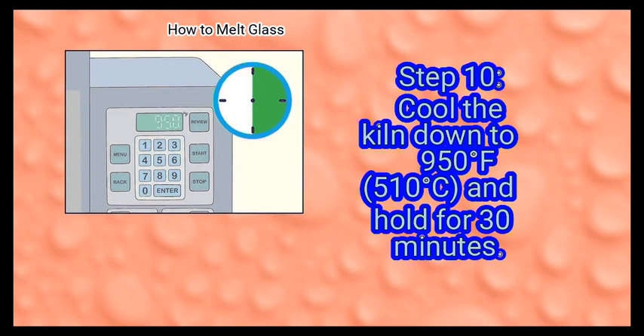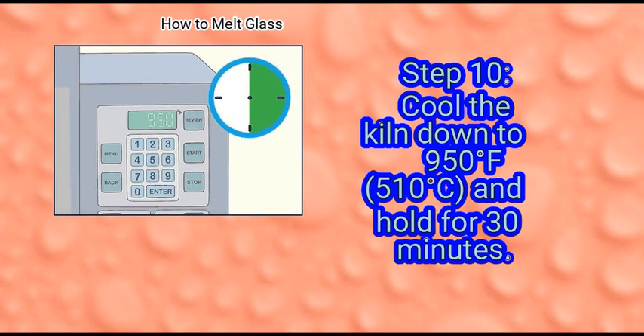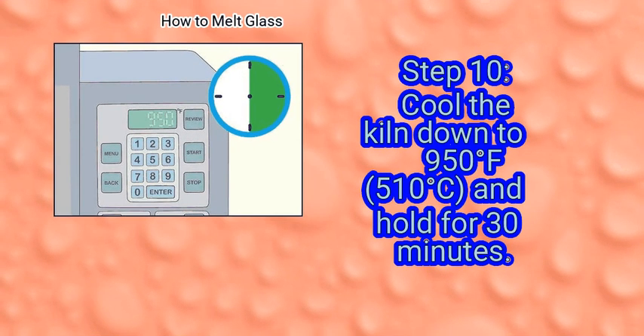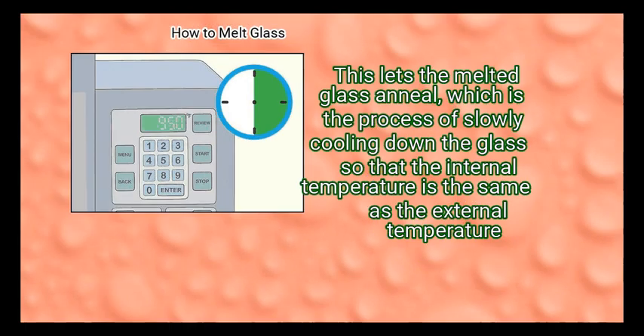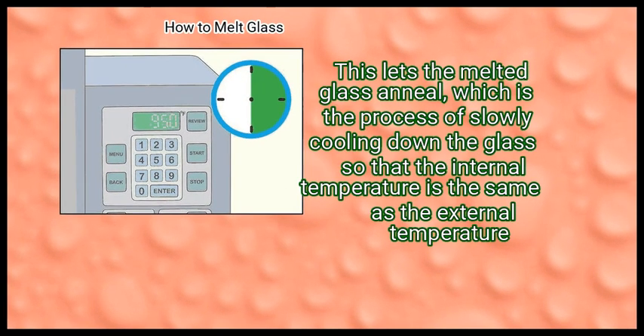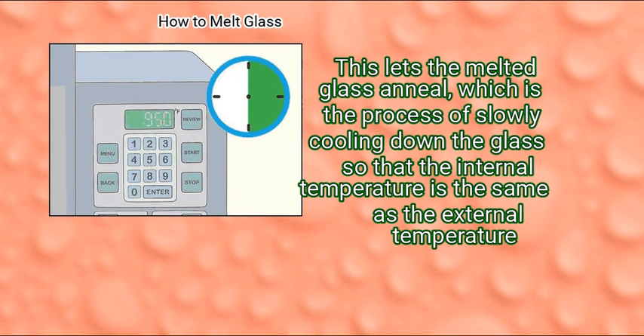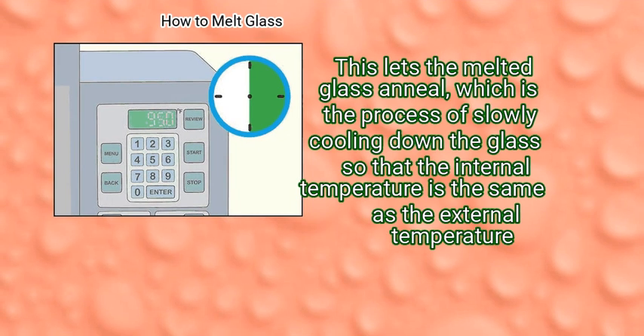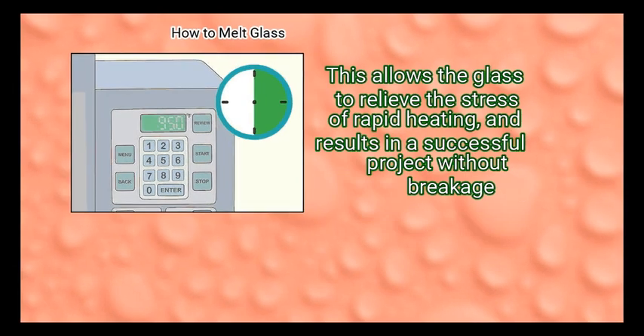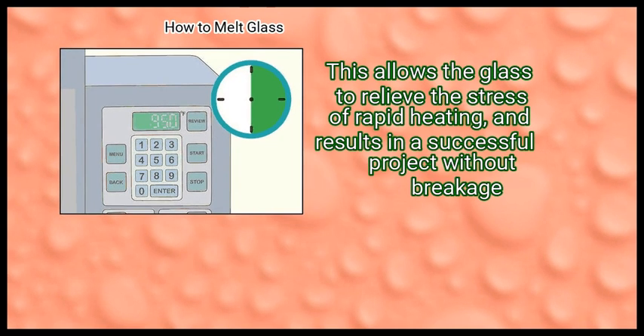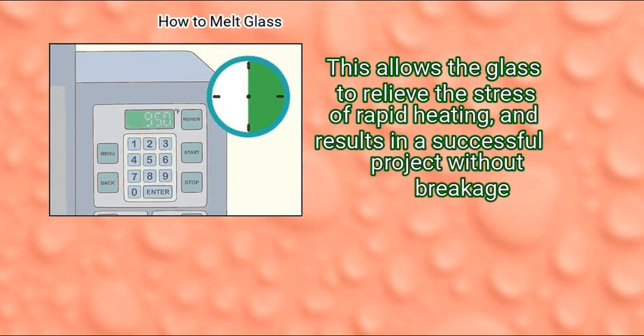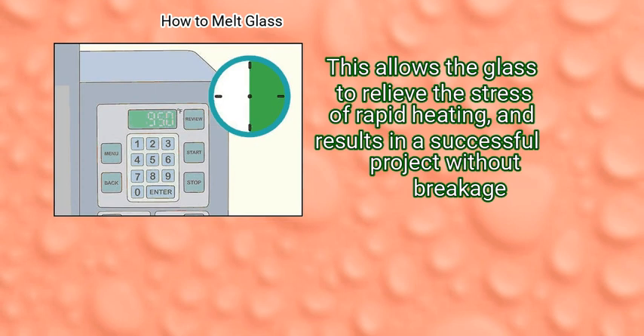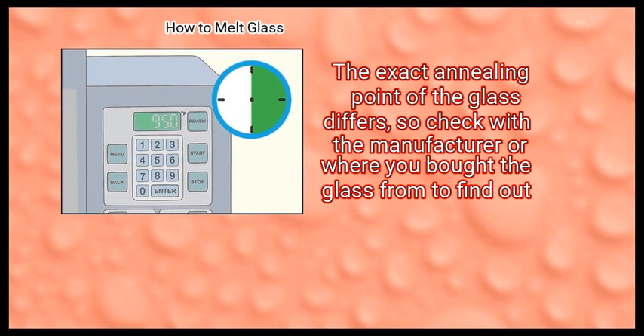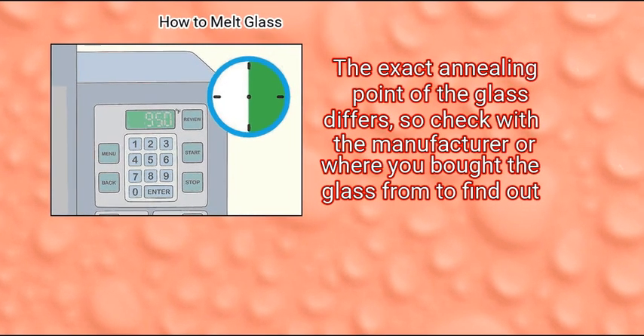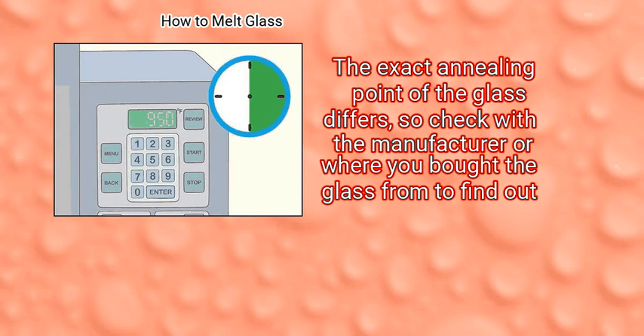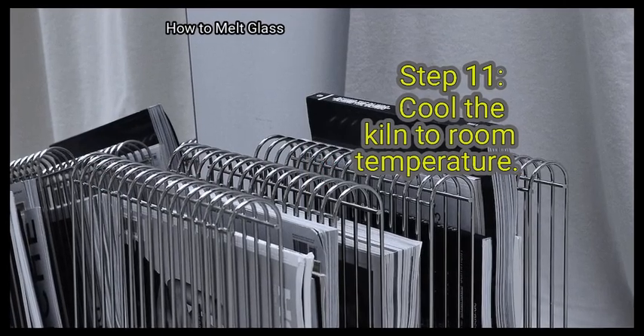Step 10. Cool the kiln down to 950 degrees Fahrenheit, 510 degrees Celsius, and hold for 30 minutes. This lets the melted glass anneal, which is the process of slowly cooling down the glass so that the internal temperature is the same as the external temperature. This allows the glass to relieve the stress of rapid heating and results in a successful project without breakage. The exact annealing point of the glass differs, so check with the manufacturer or where you bought the glass from to find out. Finally, cool the kiln to room temperature.